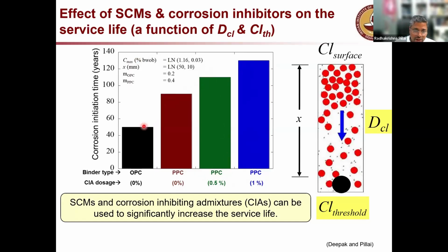So significantly, the message from this slide is that when you use fly ash or slag, those kinds of SCMs, supplementary cementitious materials, that's what we call them, the service life of the structure can significantly increase. Not like increasing by a few percentage, no. You can see here from 50, I'm able to even get up to about 120 plus. So more than double is the point. So the message here is there are two parameters which we have to worry about.